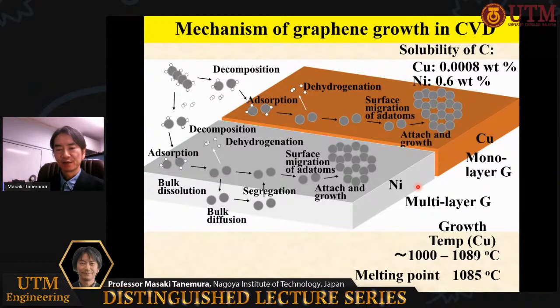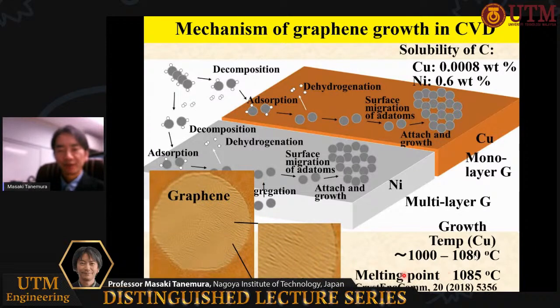The agglomeration of carbon atoms into the honeycomb structure easily occurs at elevated temperature, because the movement of carbon atoms occurs very easily. So, for the copper case, usually the growth temperature is about 1000 degrees, close to the melting point, so that we sometimes observe wrinkles on the surface.